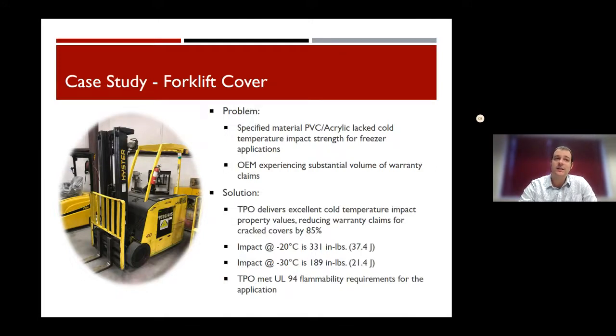And what they were finding is, as these forklifts were used inside freezers, when the temperature was getting really low, the PVC acrylic was very brittle. Imagine inside of a cold storage warehouse, someone knocks into a shelf and a 30-pound frozen turkey comes flying off a shelf. It was landing on these parts and shattering them.